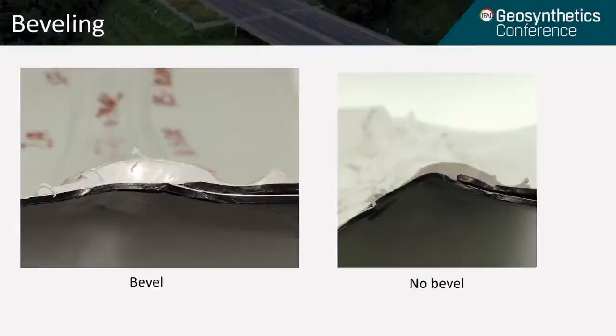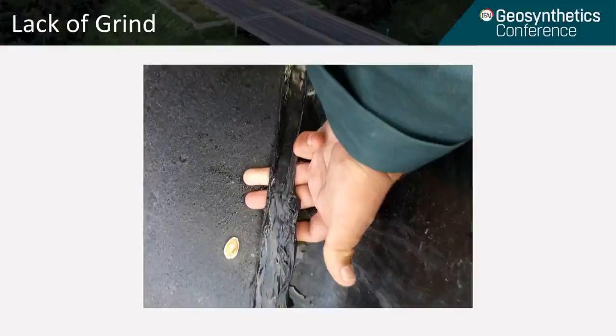In this case, beveling was properly performed in the sample on the left and improperly performed in the sample on the right. Even if the sample on the right passed peel and shear, that sample should be rejected and the operator made to redo a new trial seam. It's important to have technicians present when the actual extrusion welding is being performed because you cannot see conditions like missing grind once it's been welded.